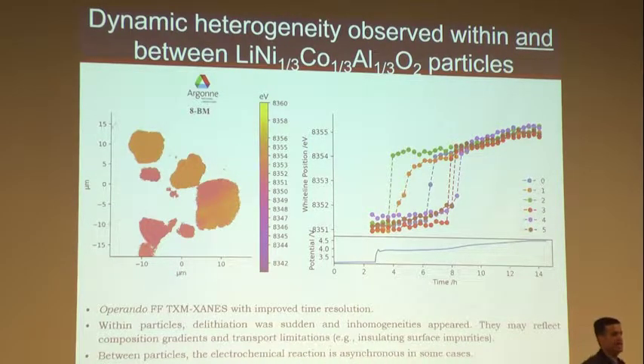Now, instead of looking at a single crystal, I'm looking at an agglomerate of primary particles. This is how commercial materials look like, by the way. They're meatballs, literally meatballs. They really look like meatballs. They're round, they have small particles, and they're really densely packed. And so in this case, we're not able to resolve the primary particles, but we're able to see how these particles go from lithiated to delithiated by following the nickel oxidation state.